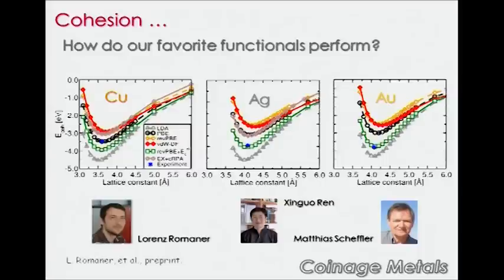For the cohesive energy, copper is perfect, just lies on top of experiment. But if you look at the cohesive energies of silver or gold, then you're quite surprised. So the cohesive energy is wrong by 1 electron volt or something like that. So that means that even if you're calculating supercells and nanostructures and whatnot, it seems that we don't even fully understand the most simple materials. So cohesive properties really give us a headache.